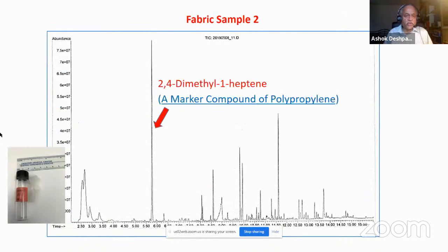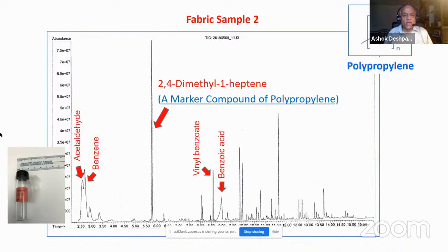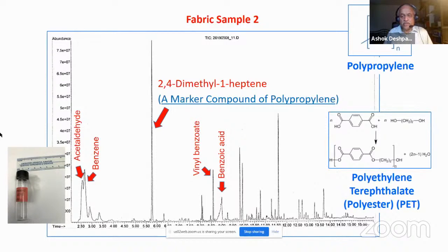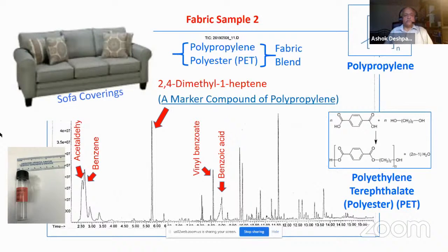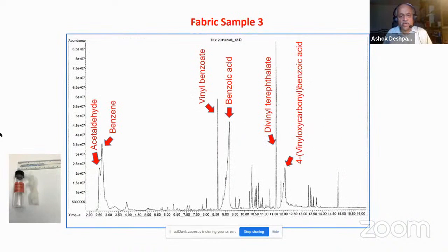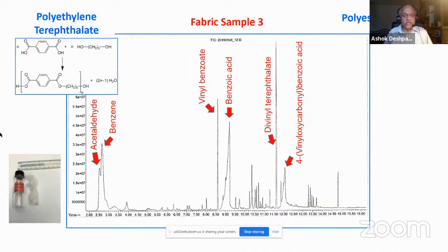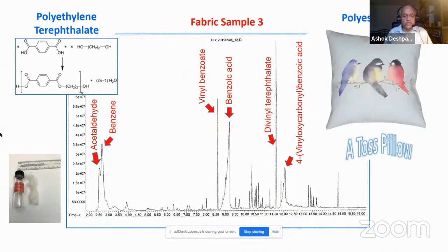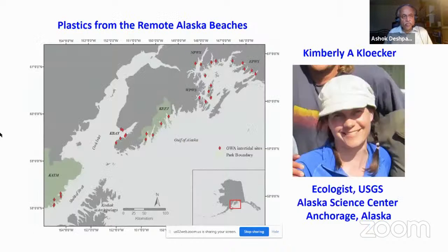The second sample contained a signature of polypropylene and it also had a signature of PET. So we call it a blend of PET and PP. The third sample only contained the signatures of polyethylene terephthalate. So we call it PET. We received plastic samples from Kimberly Kloecker from USGS. The samples were collected in the remote shorelines of northern Gulf of Alaska.